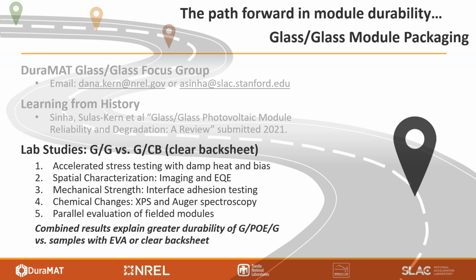In this project, we combined accelerated stress testing and non-destructive spatially resolved characterization with more destructive analysis of mechanical strength and changes in chemical composition. From these studies, we show different degradation mechanisms between glass-glass and glass-clear backsheet, including effects of potential-induced degradation and moisture ingress. We concluded that glass-glass modules using POE as the encapsulant are more durable than those with EVA or backsheets. In parallel, I'll show just a few observations in field-weathered glass-glass and glass backsheet modules to help discuss things like the relative mechanical strength and operating temperatures in outdoor environments.